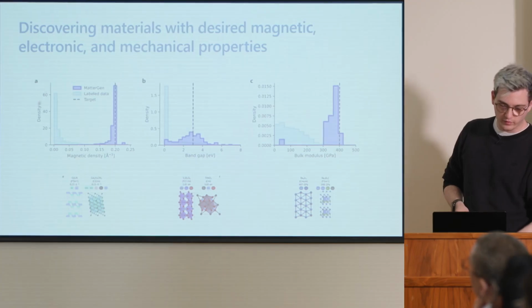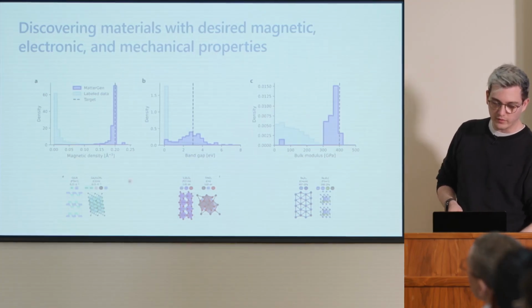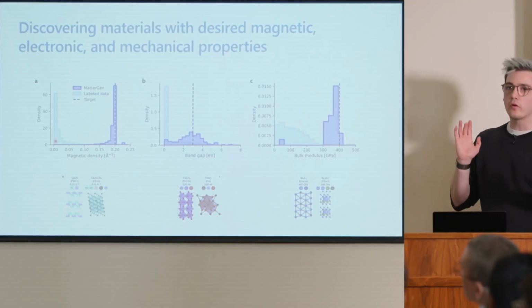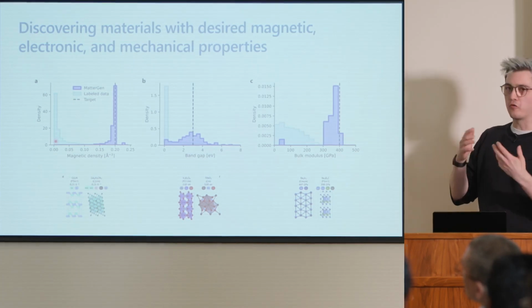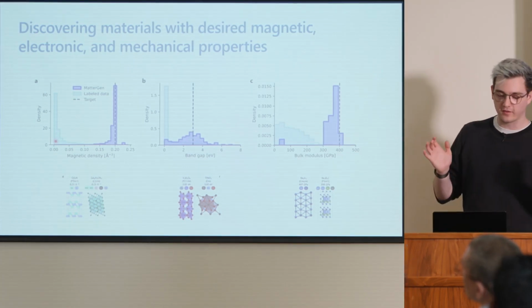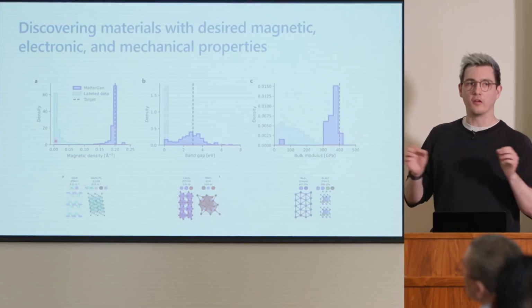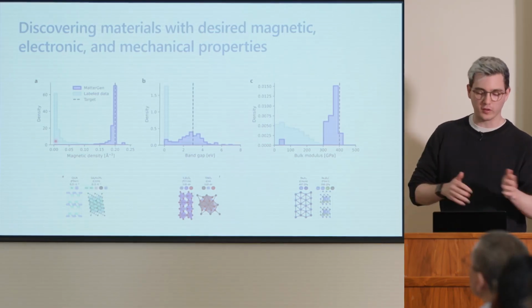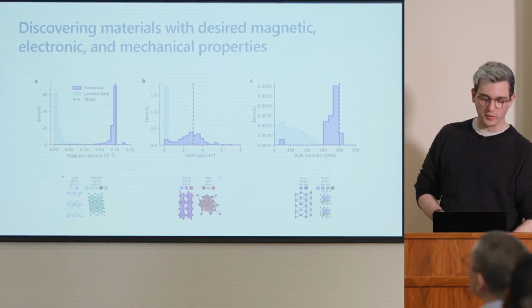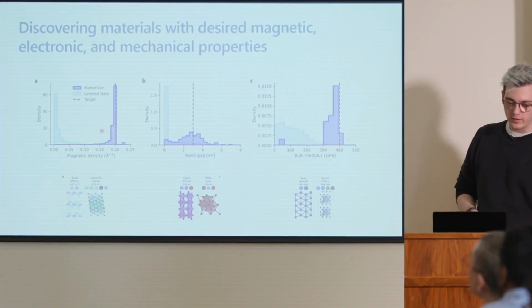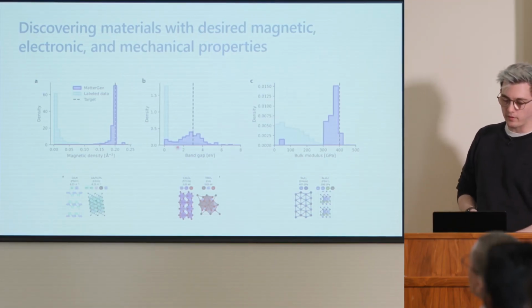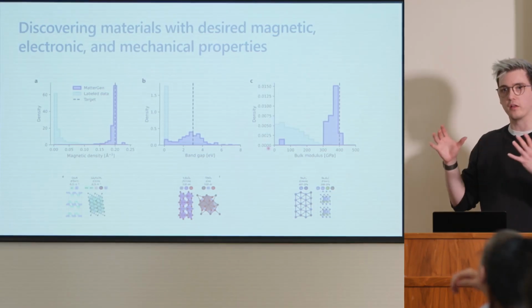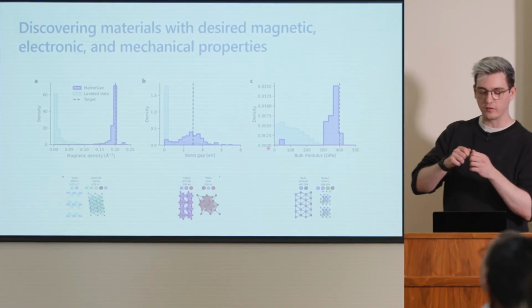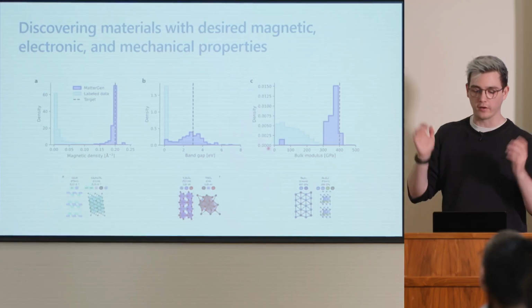The first one is the magnetic density. It's a proxy of how strongly magnetic something is, even though the magnetic density on its own doesn't tell you that. There are more checks you have to do, but it's kind of the first approximation that we could find. We looked at band gap, and we looked at bulk modulus, and bulk modulus really tells you how hard something is. So diamond is really off the charts, for example, because it's extremely hard.